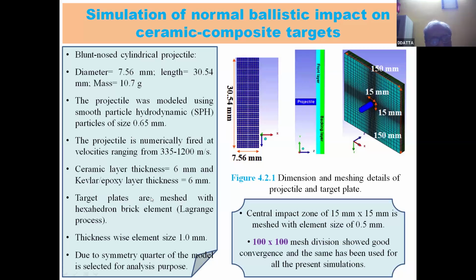Okay, so target plates are meshed with hexahedron brick element. It is an 8-node brick element. One thing is very important in dynamic work, that we should not go for very higher order elements in case of dynamic simulation. In the stress analysis problem in the previous part, we had seen the solid element was taken as a 20-node brick element. But here we cannot afford to do that, because if we take a 20-node brick element, then in the actual deformation domain, it can get heavily skewed. So there may be a problem in the simulation. Simulation may stop. So simpler elements like 8-node brick elements are preferred. That has been done.